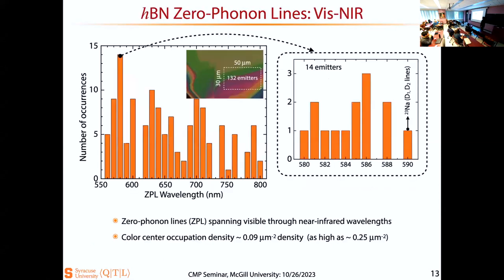Okay. Now, in boron nitride, for a given sample, I have found color centers with a zero phonon line going from 550 all the way to 804. So 804 nanometer is the longest wavelength which I have personally observed. The longest I have seen in the literature is 930 nanometer. That's the longest I've seen, maybe because we always use a silicon photodetector, which has a cutoff around 1 micron.